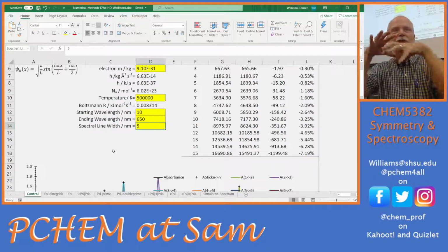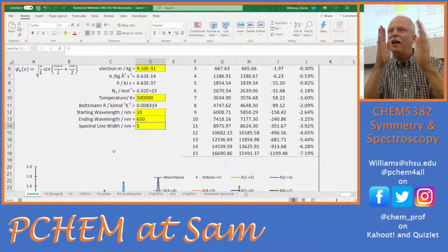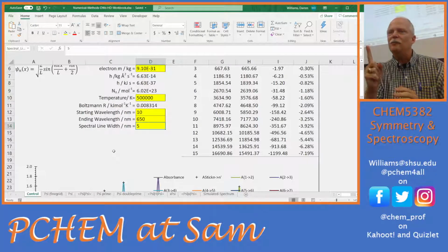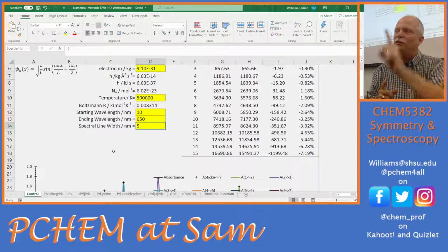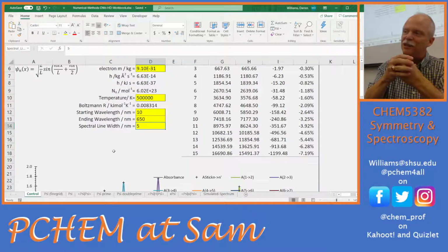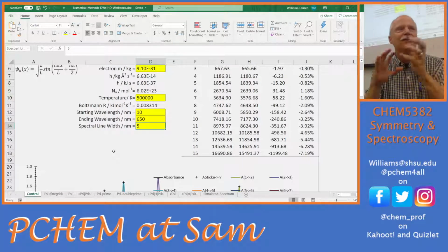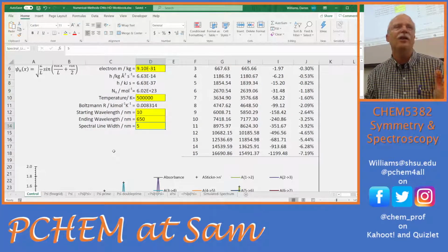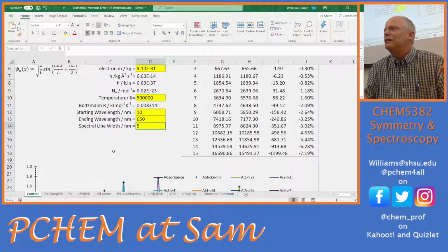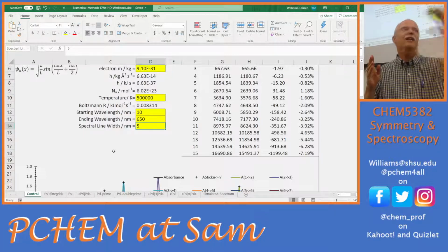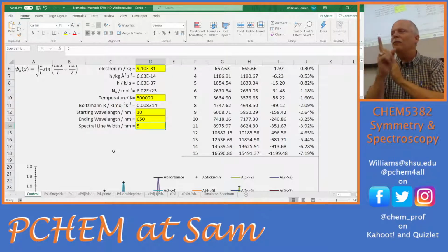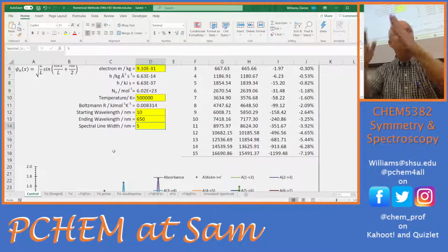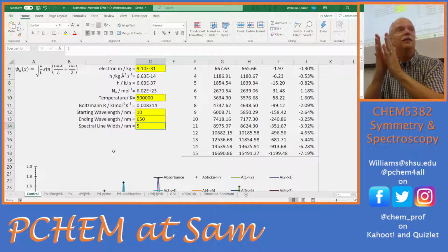If you have a molecule in an amorphous environment, you're going to have a wavelength here and a wavelength here and a wavelength here. So the fundamental transition for this molecule on the outside edge is different than the fundamental transition for this molecule on the interior. And the interior looks different for all the different molecules because you have fractures and all kinds of garbage in the whole area, impurities. It doesn't dramatically change the wavelength. It's still the fundamental, but it spreads out the peak with amorphous. In a crystal environment, you get really sharp peaks.